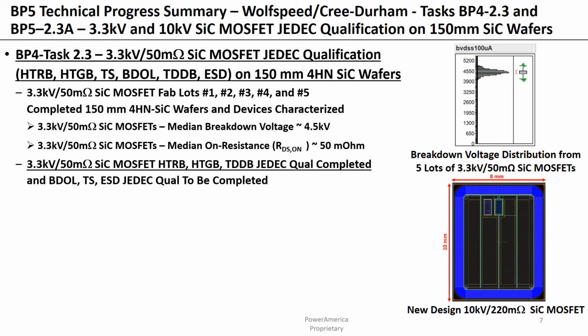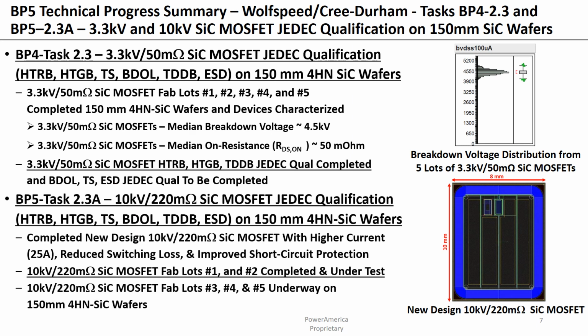In addition, we've made significant progress on JEDEC qualification, including successfully qualifying high temperature reverse bias JEDEC qualification, successful high temperature gate bias JEDEC qualification, and TDDB JEDEC qualification completion. And we're working on body diode operating lifetime, thermal shock, and electrostatic discharge JEDEC qualification, which need to be completed. On budget period 5, we are working on the 10 kilovolt, 220 milliohm silicon carbide MOSFET JEDEC qualification. This is all on the 150 millimeter wafers.